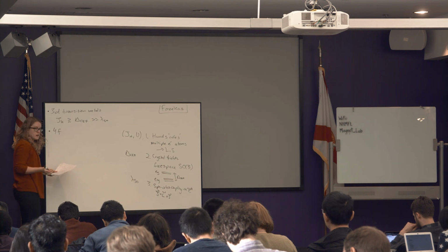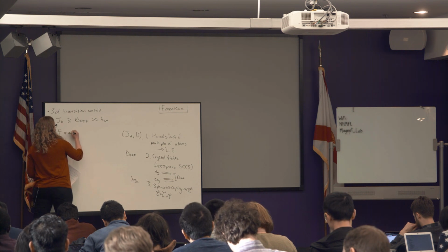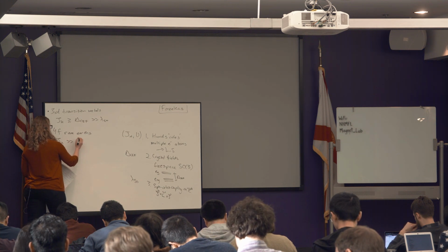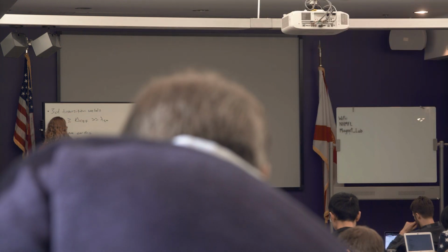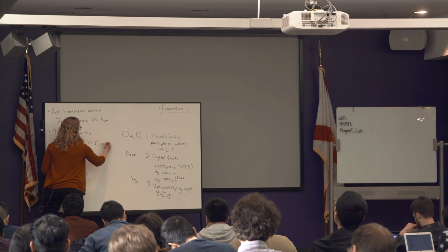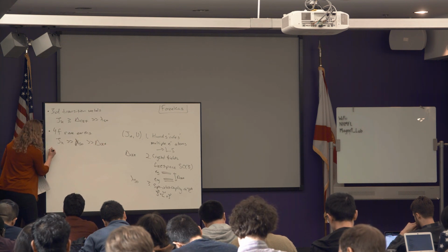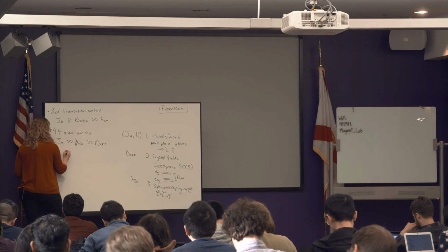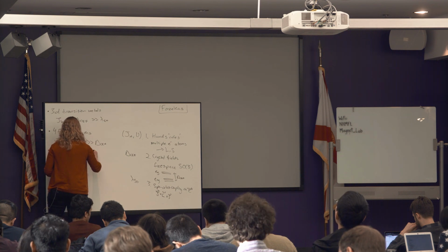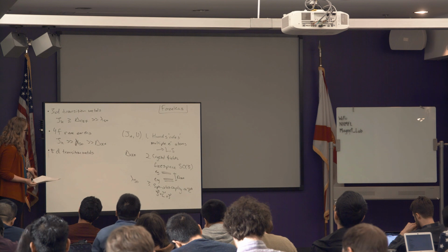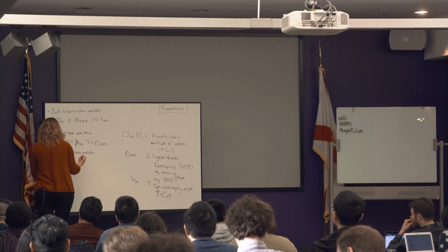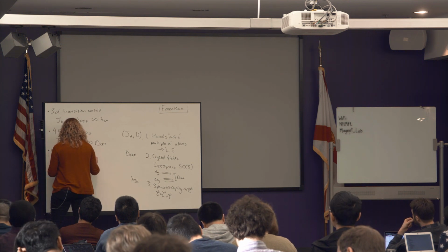When you look at 4F rare earths, this is actually even easier because your Hund's coupling or Coulomb interaction is very, very large. Your spin-orbit is your next largest term, and then your crystal fields end up acting as your small perturbation. And then finally, we'll talk about the iridates, for example, so 5D transition metals. And it's only recently that people have really looked at magnetism seriously in these systems, where all of these energy scales are on the same order of magnitude.